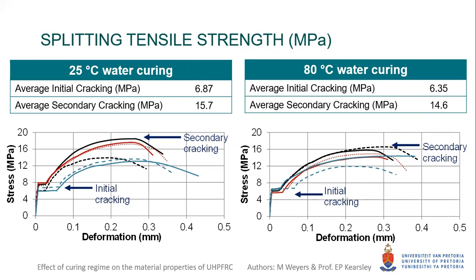The stress deformation graph for the 28-day splitting tensile strength for the cylinders is shown in the figure. Two load peaks can be seen in all the results, with the first peak occurring with the initial or first crack, and then a second peak forming as a result of the residual strength of the fibers. Although no significant difference can be observed in the initial cracking strength, the specimens cured under conventional curing conditions reached a higher secondary peak strength compared to the heat-cured samples. A higher variation in the secondary cracking strength for the specimens cured in the 25 degrees Celsius water was observed.